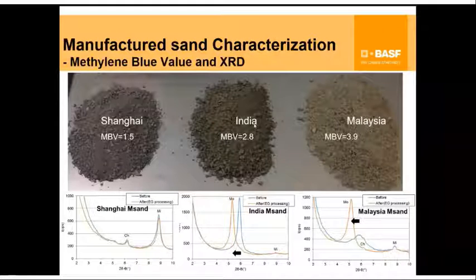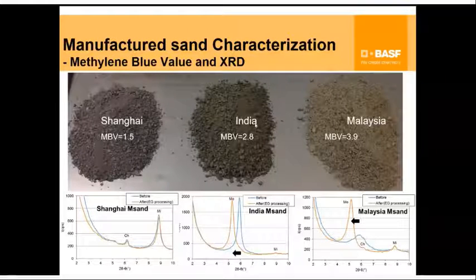So here was an experiment that I did when I was in India to try to characterize what kind of clay we have. We picked up sand from Shanghai, Mumbai, and Malaysia. Malaysia won this battle. It has the highest amount of expandable clays. The MBV value, or the methylene blue value, is one of the ways to determine how bad your sand is in terms of clay. But it doesn't tell you how much of that is expandable clay, because methylene blue value will give you a response to most clays.